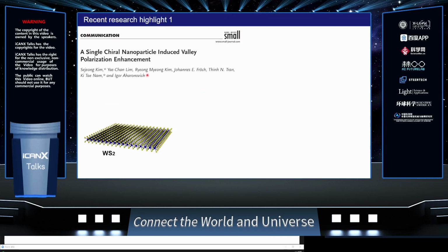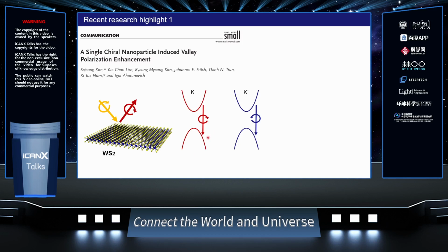The first one was published last year, and is titled a single chiral nanoparticle induced valley polarization enhancement. And to put valleytronics in a nutshell, if we excite WS2, for example, with right-handedness circularly polarized light, the PL of WS2 also has right-handedness and vice versa. This is due to the two valleys in the momentum space, which preserve the opposite handedness. Therefore, it enables us to selectively excite one of the valleys by just using circularly polarized light.